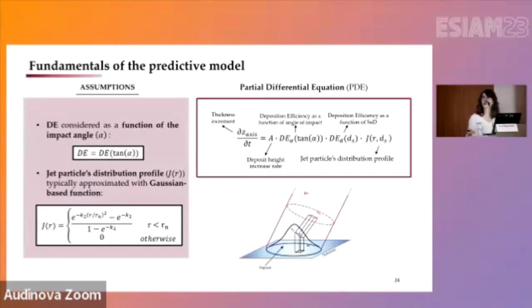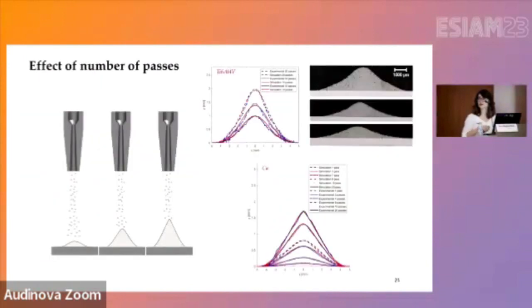So the model is based on considering the deposition efficiency as a function of the angle of impact, considering deposition efficiency as a function of the standoff distance with respect to the substrate, and generally considering the particle distribution profile as a Gaussian-based function, but we have the possibility of implementing any other type of function inside the model. So we get to a series of partial differential equations that is based on the physics of the deposition process, and is able to predict the shape of the track as a function of different process parameters. Here you can see the results that we could get from this analytical model for two different materials, Ti64 and copper.